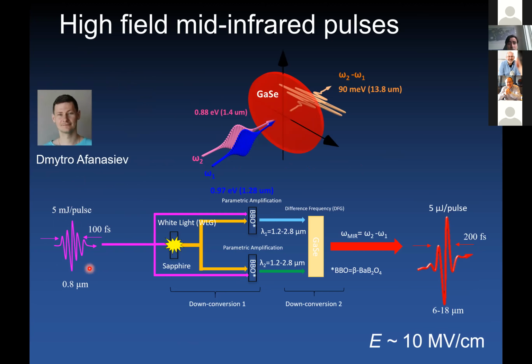So this is the output of a titanium sapphire laser, and this system has a series of optical parametric amplifiers that are seeded by the same white light and difference frequency generation that eventually produce a pulse that we can control in its wavelength between 6 and 18 microns, and carry an electric field of the order of 10 megavolt per centimeter. So a significant fraction of the electric fields that you have in matter.